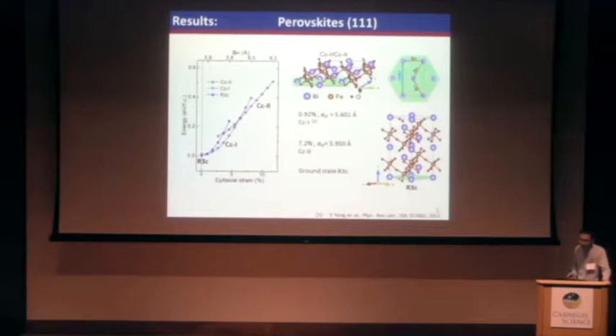First, let's look at the perovskite phases. At zero strain, since it's the 111 substrate, it's the R3c. And then when it goes toward the tensile side, it first becomes the Cc-I phase and then the Cc-II phase. Those phases look like this. As we can see, the epitaxial strain is quite large.